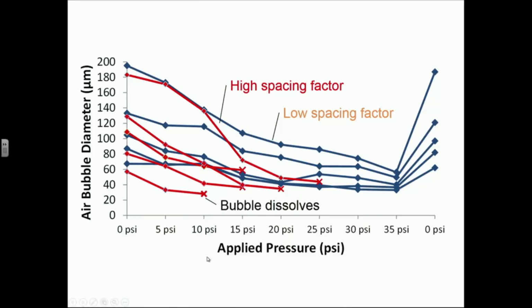I'm showing applied pressure at the bottom. So here's atmospheric pressure. Here's 5, 10, 15, all the way up to 35, then back to atmospheric pressure. And this is the air bubble diameter that we measured. Notice here that both of these red are the high spacing factor bubbles, the bubbles far apart. The blue are the low spacing factor bubbles, close together. These bubbles are both very similar in size originally, but the high spacing factor bubbles behave similarly up to about 10 psi. But about 15 psi, they start to perform very differently.